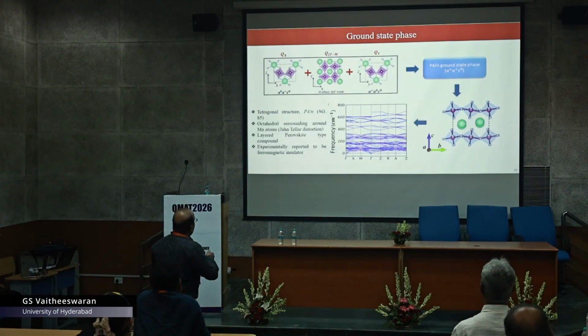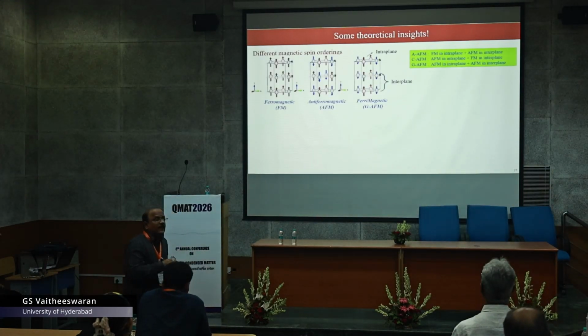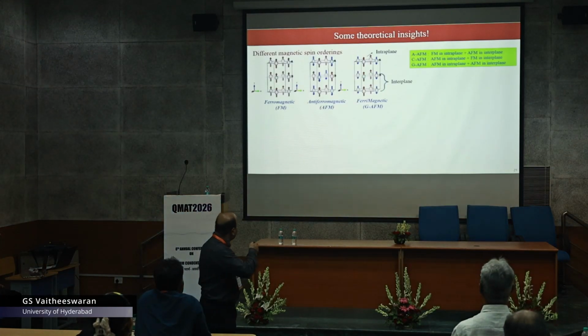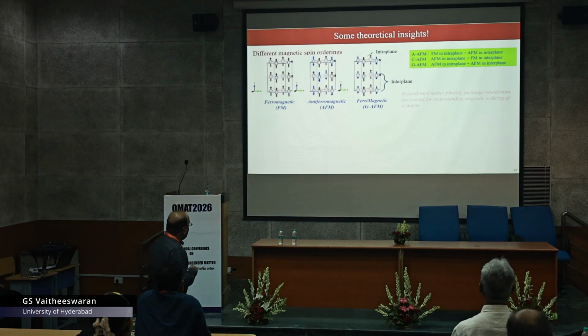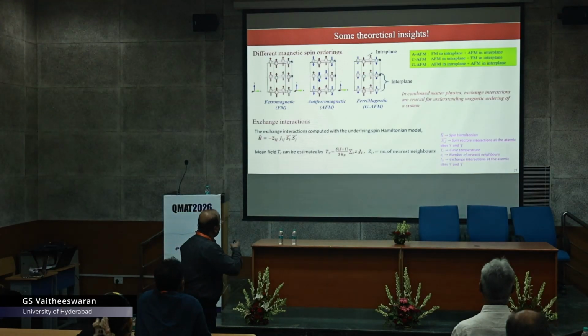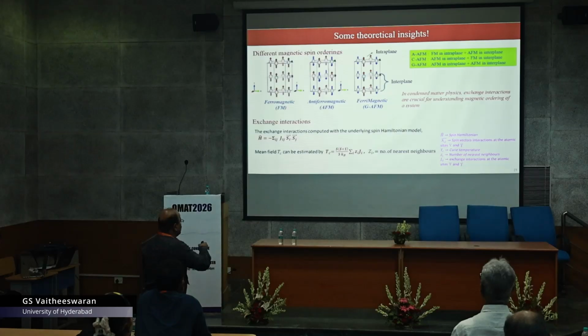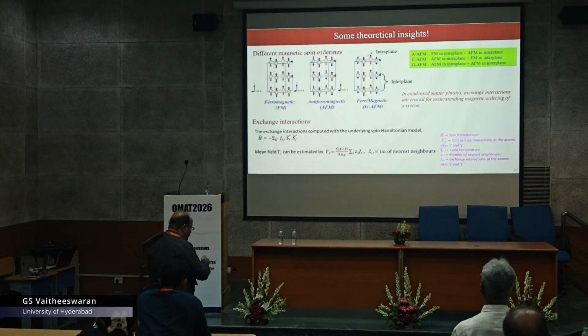Fine. So now what else? How about the magnetism? We tried different magnetic configurations, and then we concluded that the total energy is more favored for a ferromagnetic ground state. That is fine, and then we took the standard traditional Heisenberg exchange interaction and tried to compute the Curie